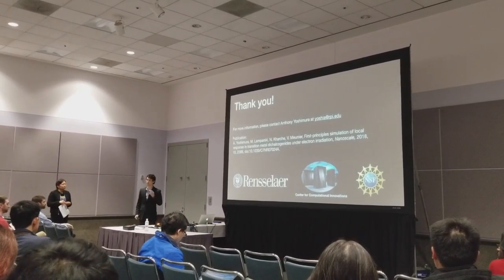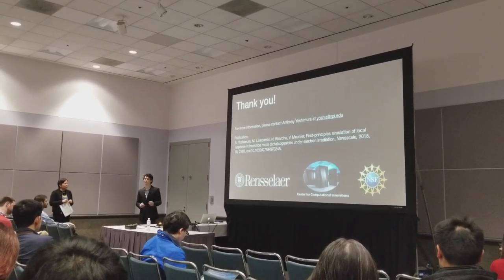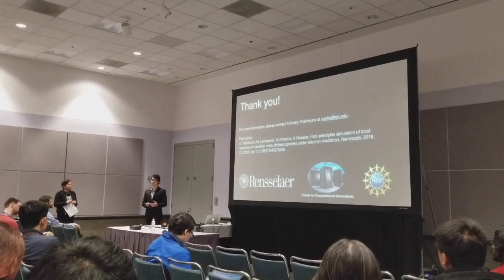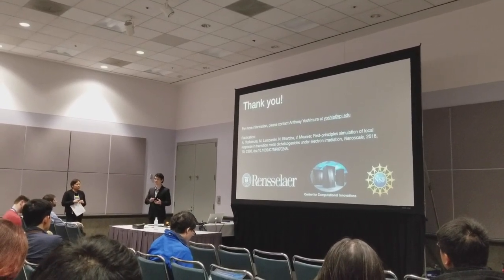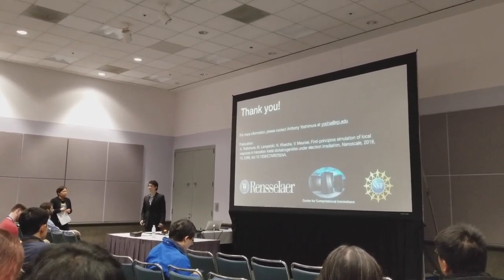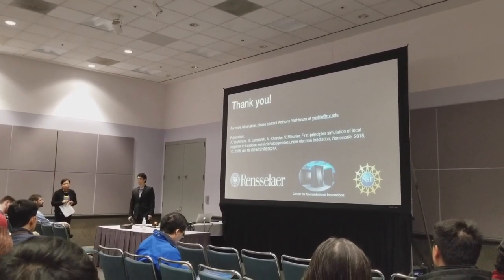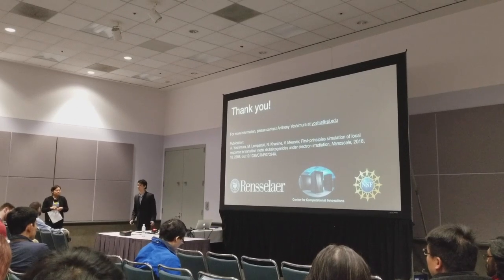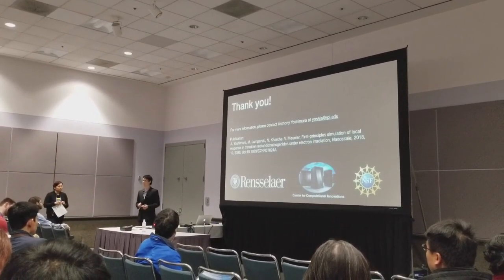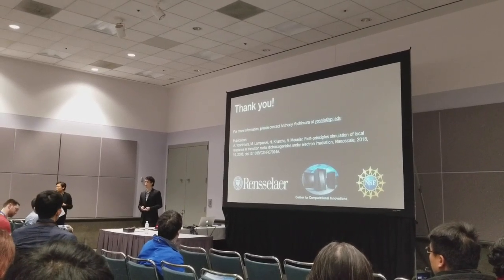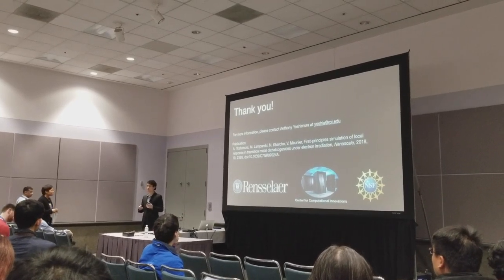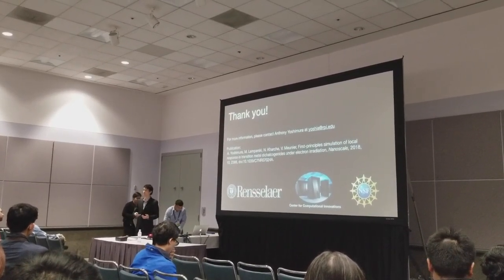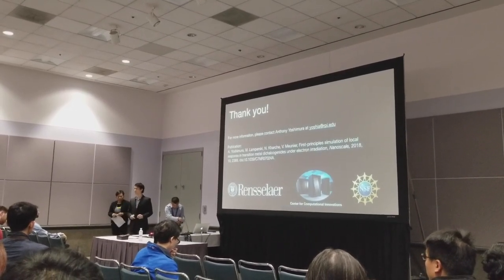That's a great question. My model only considers elastic collisions, so heating of the sample is not accounted for. That would be more of an issue with heavier atoms that have a higher electronic density. Also, if you increase the beam power, the energy imparted onto the atoms can dissipate as heat. That is something we should consider, especially for heavier atoms. For heavier atoms you'd see charging and radiolysis, but the overall process should remain the same — those processes would tend to lower our displacement thresholds, but we could still plug them into our cross-section to find the relative rates. It's just a matter of finding those new displacement thresholds.